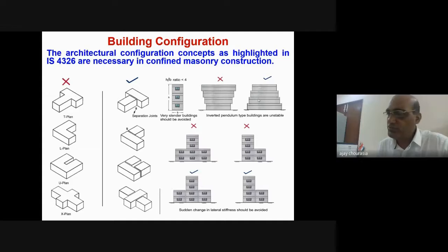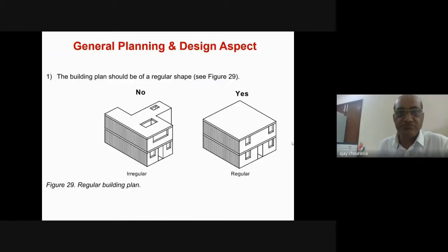How much separation gap needs to be provided? That is 20 mm per story height, per number of stories. According to that, you have to provide this separation gap. Again, very slender buildings should be avoided. Apart from that, inverted pendulum type buildings are unstable and should not be permitted. Even a sudden change in stiffness in elevation should be avoided by giving a proper separation gap. So regular buildings, as I mentioned, are very good. Irregular buildings should not be allowed.